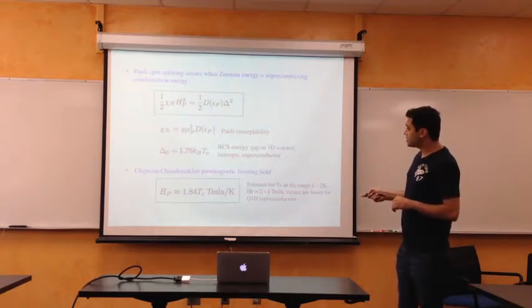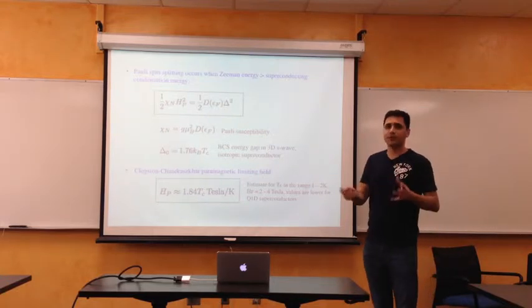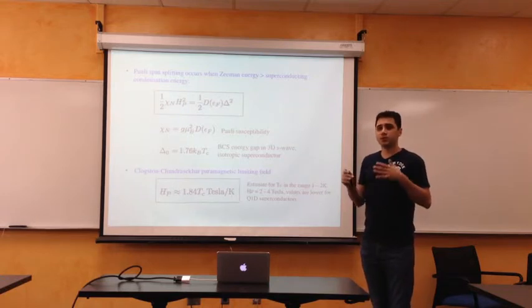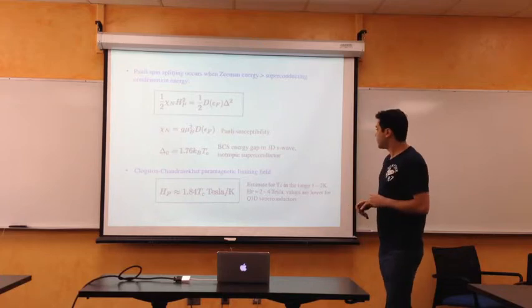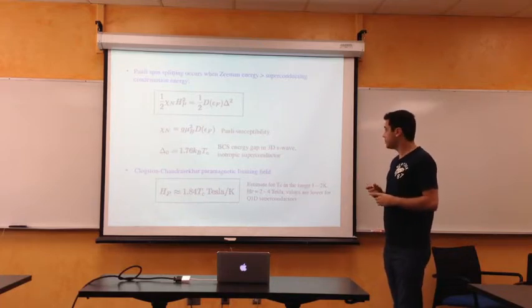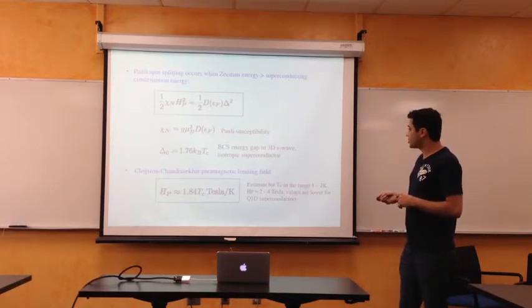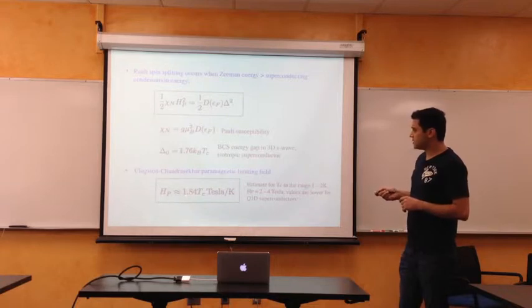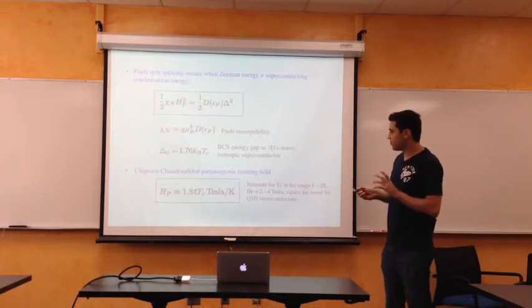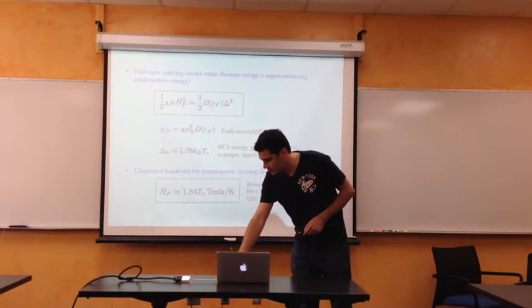And this result is for an isotropic 3D superconductor, which is not exactly the case of our example, but it gives us a rough estimate. In fact, for a lower dimensional superconductor, this result is even lower than that—I think it's on the order of 1.5.